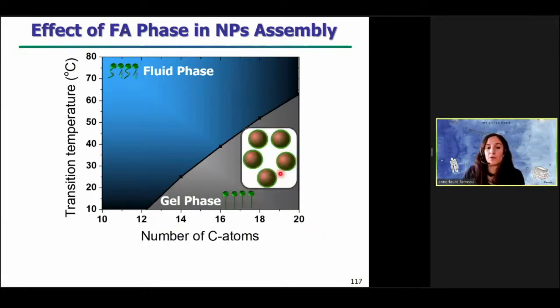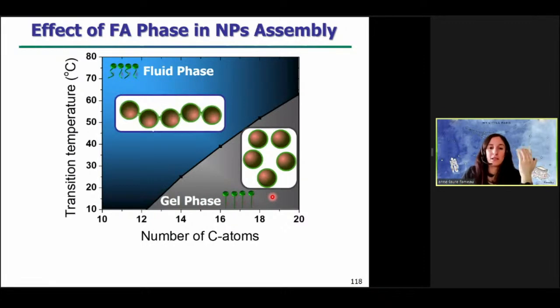Then we just put nanoparticles with all the fatty acids in a gel phase. We apply the magnetic field in this direction, but we didn't see the formation of filaments. So that shows that when fatty acids are in a gel phase, they don't lead to the permanent assembly of the nanoparticles. But when you perform the same experiment for all the fatty acid soaps in a fluid phase, you always obtain the formation of these filaments when you apply the magnetic field.